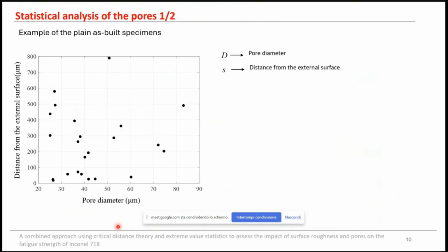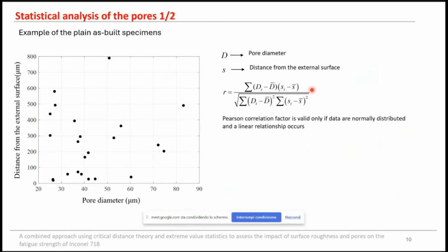Once the experimental data were collected, we started performing some statistical analysis of the pores, trying to investigate possible correlation between pore diameters and distance from external surface. We started using Pearson correlation factors, which in principle could not be applied because it has strong assumptions behind, such as that the variables have to be normally distributed and that a linear relationship must occur between them.